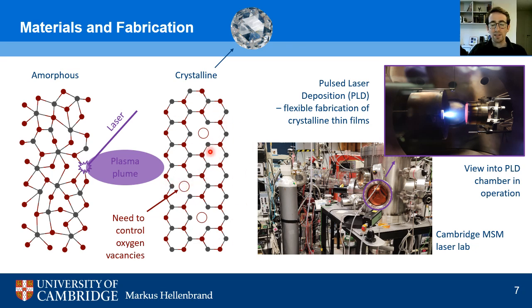And this crystalline structure is what we're trying to use to make more energy efficient computer memory. So first of all, we have to make sure that we can achieve such a nice and crystalline structure. And we can do this in our laboratory with a technique called pulsed laser deposition. So this is how our lab looks, and what we need for the pulsed laser deposition is the orange box in the back, which is the laser, and a vacuum chamber here in the front.